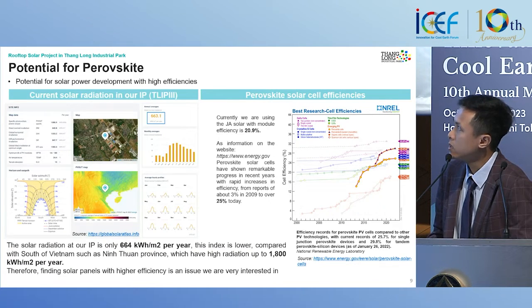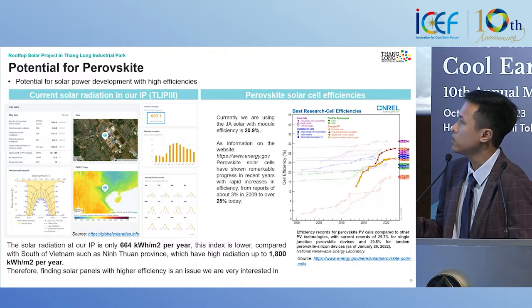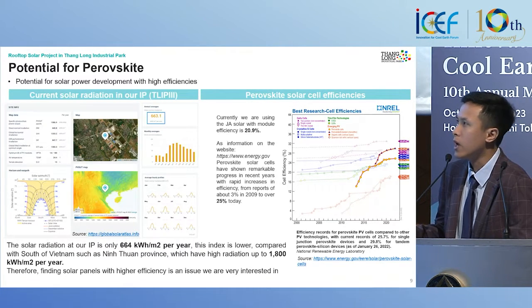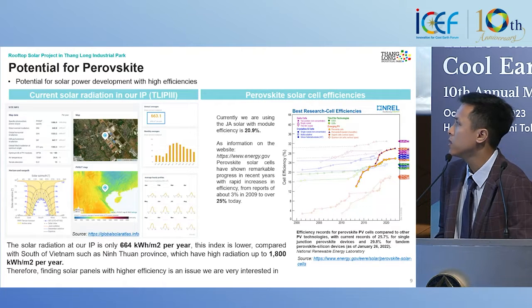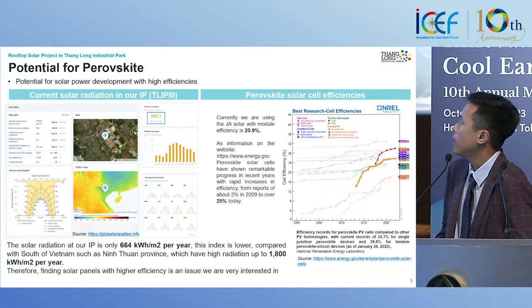And the third reason, as you can see on the screen, from the data on the website Global Solar, the solar radiation in our energy park, I made a sample in Tip number 3, is only 664 kilowatt hour per square meter per year. This index is lower compared with South of Vietnam, such as Ninh Thuận province, which has high radiation up to 1,800 kilowatt hour per square meter.